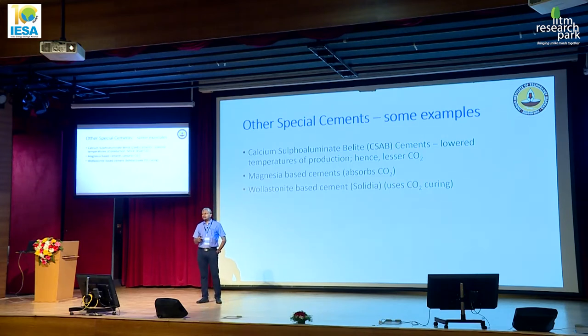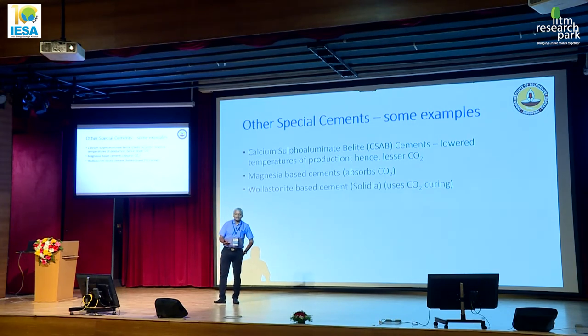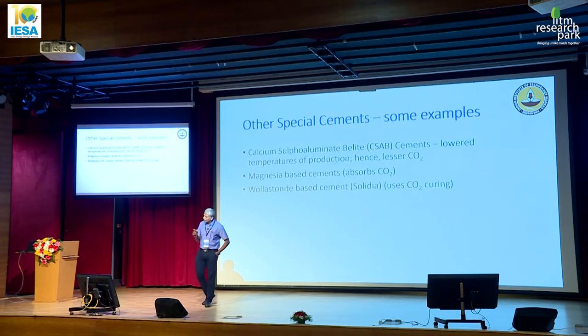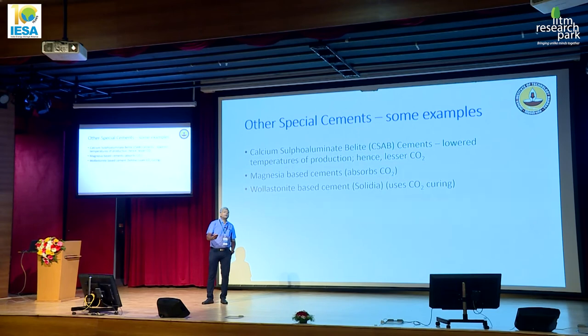There are also some new, or rather relatively new, cements, like magnesia-based cements, which are reported to have a net negative CO2 impact because they absorb CO2 during the process of their hardening. And also the wollastonite-based cement, which is calcium silicate-based cement, which is quite popular around the world, called Solidia. Again, commercial uses are still restricted. A lot of research is still going on with respect to Solidia and the need for carbon dioxide curing to make the cement.